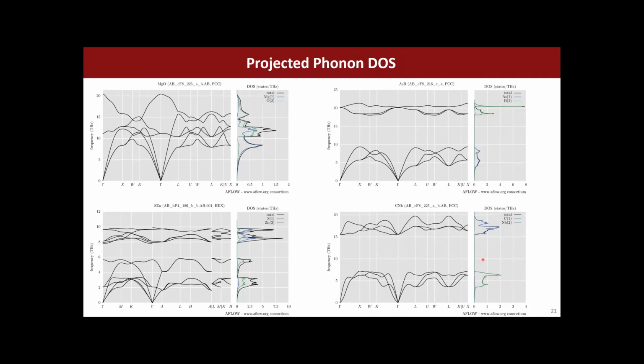When we think about the dynamical matrix, the masses are in the denominator, square root of the product of the masses in the denominator. So we can imagine that a higher mass has lower frequencies as a consequence, and that's generally true. But again, force constants also play a role. It's not super foolproof, but if you have a strong mass difference, it's very unlikely that they will overlap. And this can be used to engineer essentially your phonon frequencies.